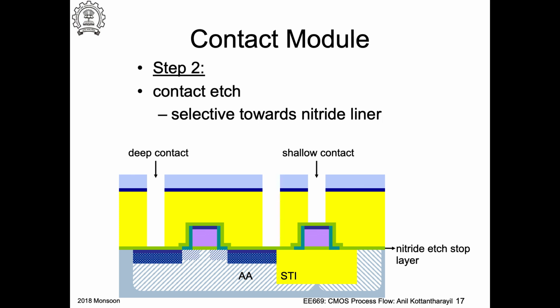So I should not end up etching the silicide, and then the polysilicon and so on. So it's safer to actually have a layer. For example, in this case, you have a nitride layer, and you can etch your silicon dioxide or phosphosilicate glass with very high selectivity to nitride. So that is the whole idea of putting this silicon nitride there.